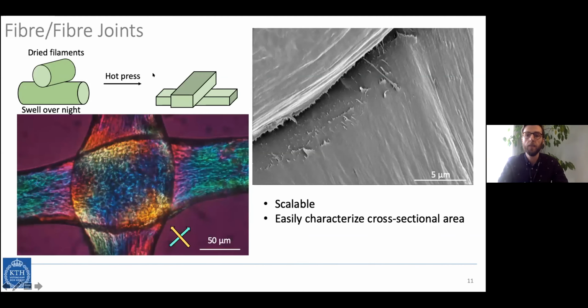If we look a little bit closer at the joint specifically under the microscope, we can see that we have aligned fibers in both the X and the Y directions. We can characterize how they're aligned within the joint using polarized optical microscopy, and look in more detail using scanning electron microscopy.